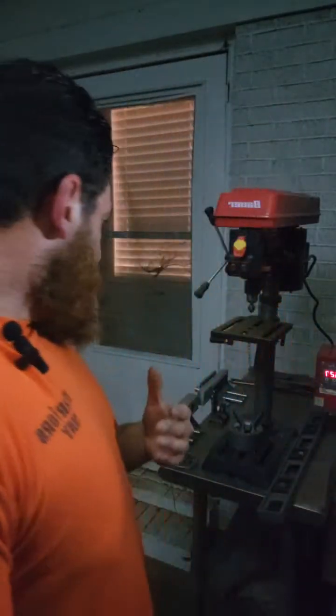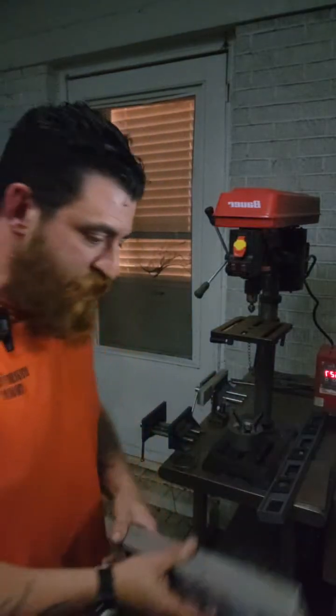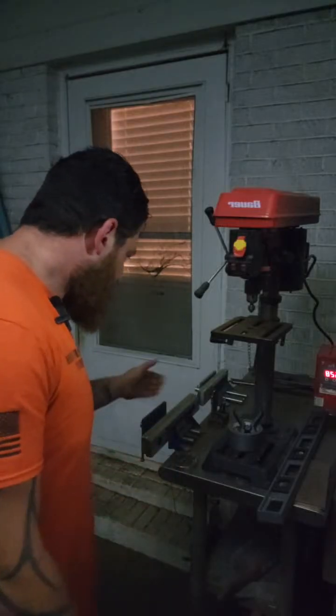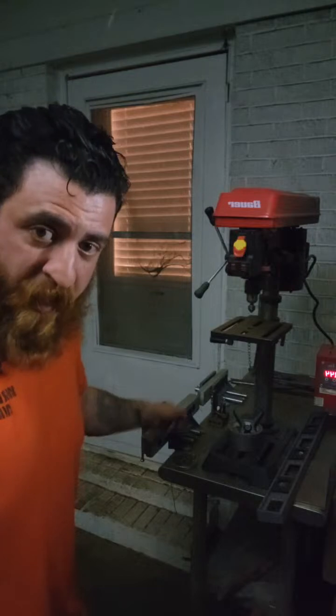I used to do the same thing and freak out. And then what I did is I started testing stuff. So you see these plates right here? These aluminum plates I have on these vices for quenching steel. I've tested cold plates, frozen plates. I've tested with air, without air. I've tested just putting them in these plates right here and closing them. Every single one got the exact same Rockwell hardness, within like 0.2 or something like that. What would be the normal variance between steel?